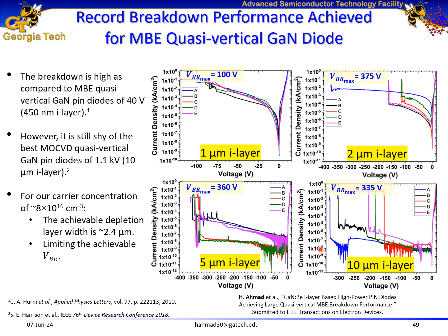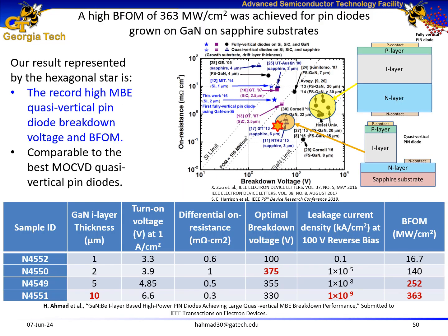One significant point that we see from comparison of the thicker devices versus the thinner devices is that the thicker devices show leakage current which is significantly lower, approximately 7 orders of magnitude lower as compared to the thinner devices. So we used a doping of 1 × 10^17 per cm³ and achieved a carrier concentration of 8 × 10^16 per cm³.